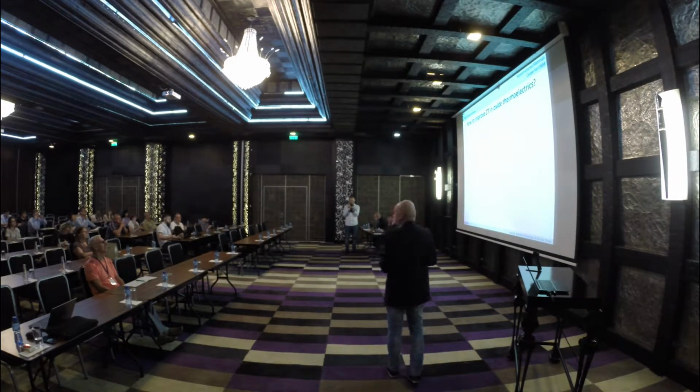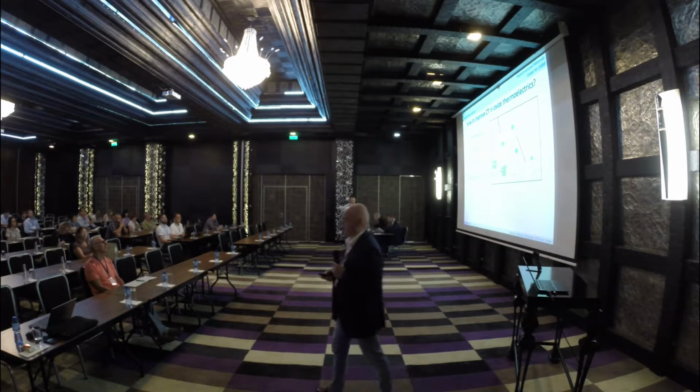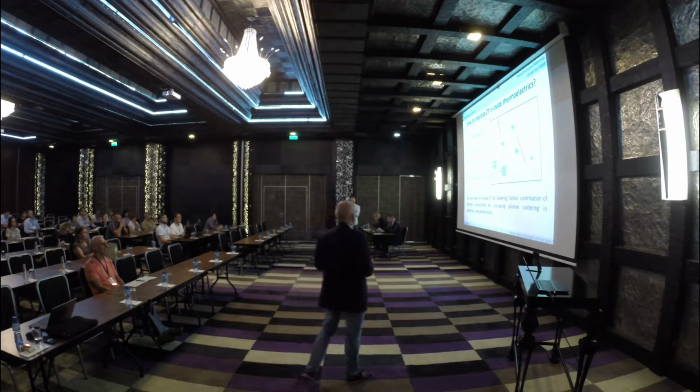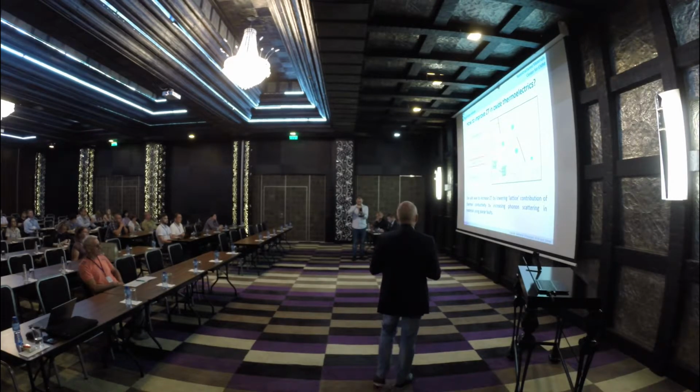So, how to improve the ZT value? There have been many tries to do some engineering in the microstructure of these polycrystalline materials, such as grain boundary engineering, some inclusions, some superstructures, so that we have some layered structures. And what we decided to do is to implement so-called planar faults into the microstructure. With this, we wanted to increase the phonon scattering, hence reducing the thermal conductivity and consequently, of course, to increase the ZT of the material.